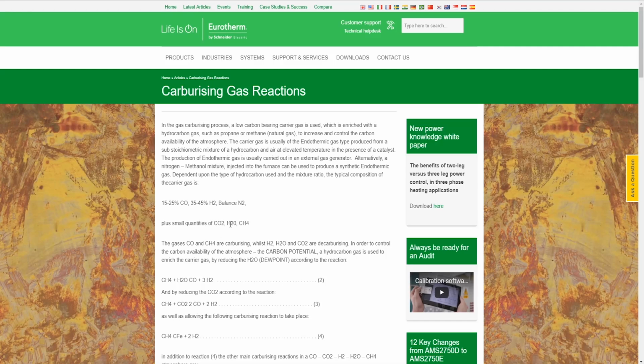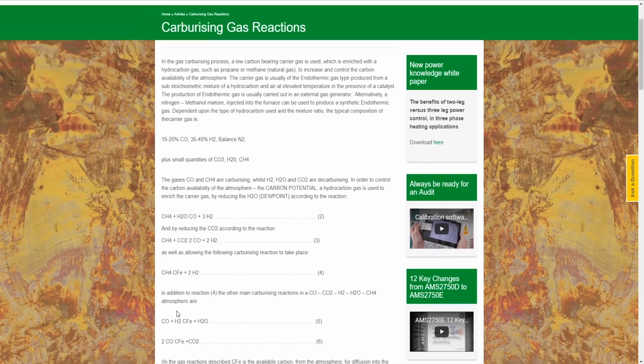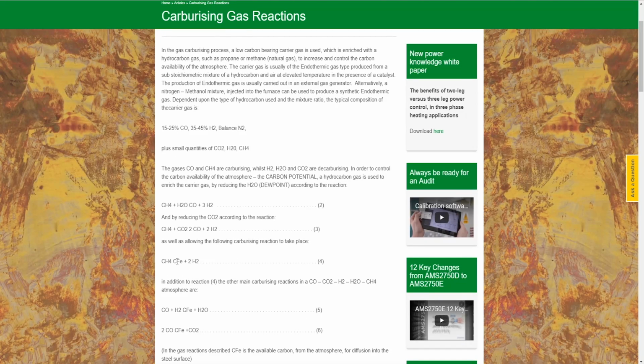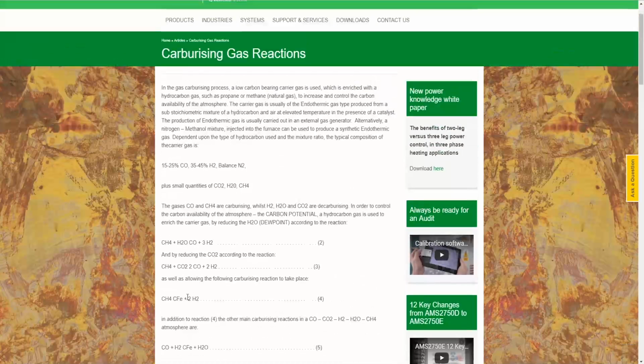So these are basically your carbon-carrying gases. The gases carbon monoxide and methane are carburizing, whilst H2O, hydrogen gas, water, or carbon dioxide are decarburizing. A hydrocarbon gas according to the reaction: methane plus water gives carbon monoxide plus hydrogen gas. And here's methane giving carbon plus iron plus 2 hydrogen. So here's the carbon inside of the iron. So basically what it's saying is that carbon monoxide and methane are carburizing, whilst H2O and CO2 are decarburizing.